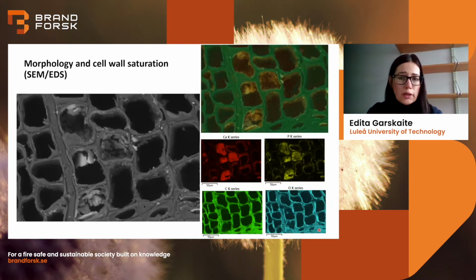So here I am showing the smallest concentration which we chose to modify wood. For this set of samples, we didn't get complete saturation of cell lumina, but we also performed EDX analysis, energy dispersive spectroscopy, and checked that we get precipitation, and that we also have in the cell walls the elements we were aiming for. So calcium and phosphorus precipitate within cell lumina, and also within the cell wall.